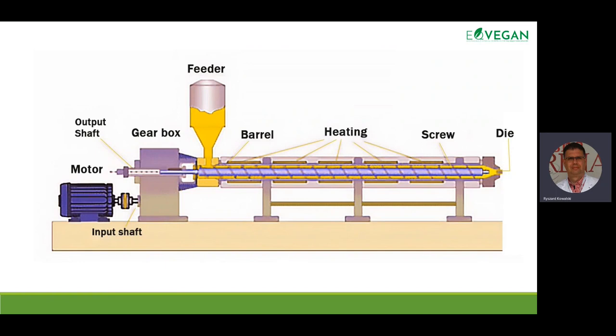During the preconditioning step, moisture is uniformly applied in the form of water and or live steam to achieve a moisture content of 18 to 25%. Water is introduced through a series of spray nozzles that atomize the water and thereby reduce the mixing load on the preconditioner. Steam is added through a manifold to the preconditioner. The plumbing for the steam supply must be designed to supply a continuous flow of condensate-free steam. If the steam added to the preconditioner contains pockets of condensate, an unstable extrusion process will result due to rapidly varying moisture contents.